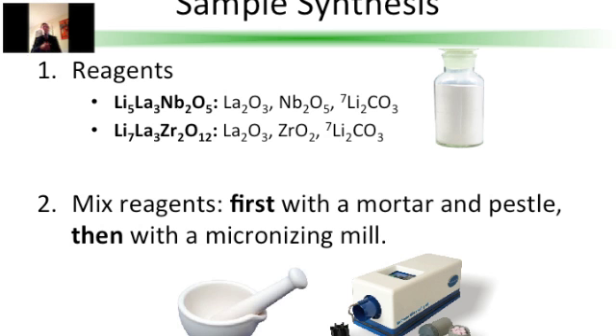Okay, so now I'd like to talk about the methods I used for the project. I first have to synthesize the lithium lanthanum zirconate and the lithium lanthanum niobate. To do this, I used a very popular technique called powder solid state synthesis, which is when you take the reagents in powder form, mix them, and then heat the mix.